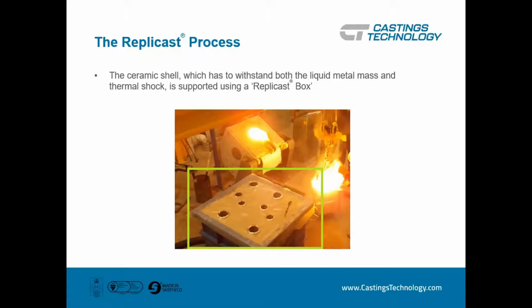So outlined on this particular photo is the Replicast box down at the bottom here, and you'll see a number of vents and also the down sprue. And what we do there is we put the shell in its entirety inside a steel box. We surround it with standard silica sand, nothing special about the sand. What is special about the process is we then put a sheet of plastic across the top. We connect the box to a liquid ring vacuum pump. And if you've never done this experiment, if you do that, you find that the sand solidifies.